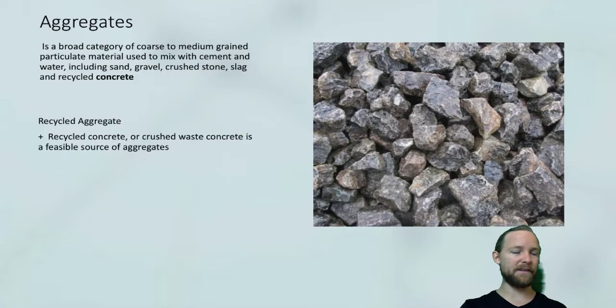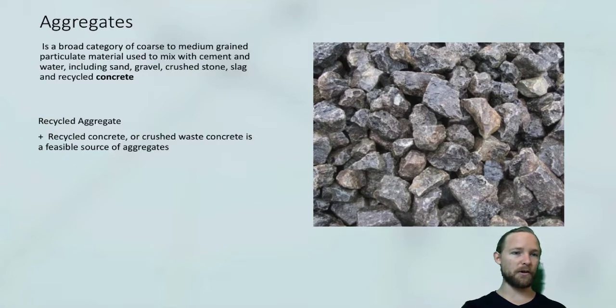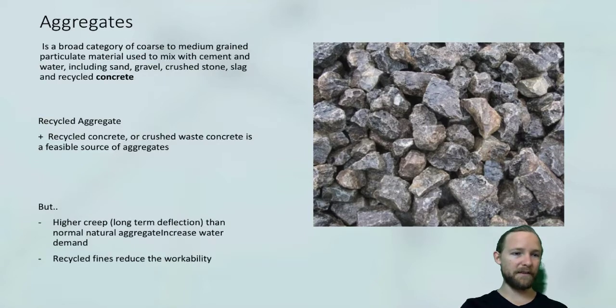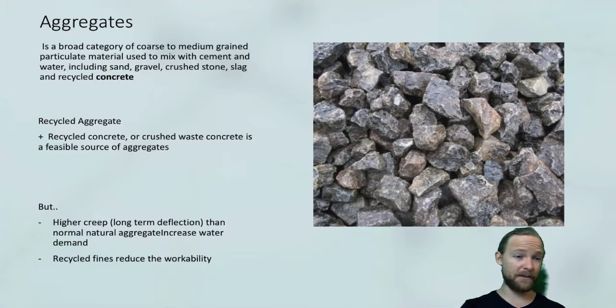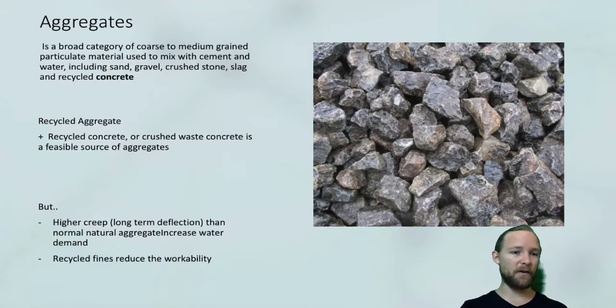The opportunity for recycled aggregate is when you use recycled or crushed waste concrete as a feasible aggregate. However, with this you're going to have higher creep, meaning long-term deflection over time will be greater, which is a key criterion for design engineers. For elements where deflection governs, this might not be the best option. The recycled fines also reduce workability, so it's better to use recycled aggregate only for the coarse aggregate.